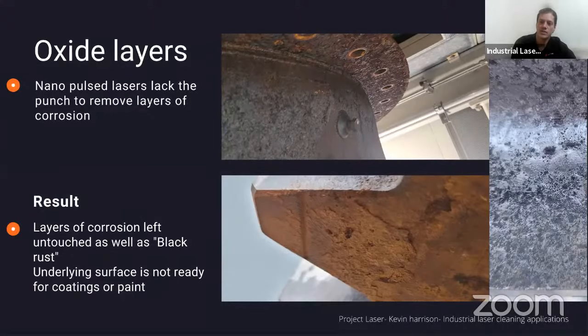On the far right, you also see black rust. These little black dots are what happens when the iron contamination is forged back onto the surface, and that then becomes really hard to remove, and it's also unsightly. So the underlying surface is not ready for coatings or anti-corrosion treatment. So what should you do? Next, please.